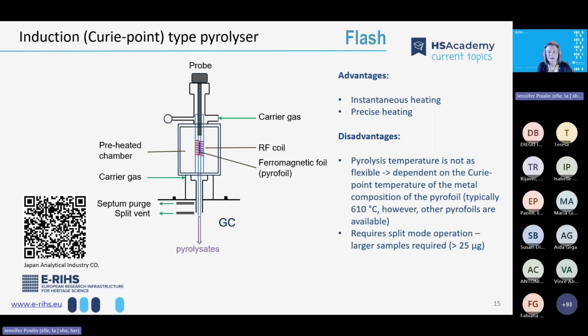So this is the induction type pyrolyzer called a Curie point. It heats a foil using a high frequency magnetic field, and depending on the Curie point of that foil, that's the temperature that you get. In our field, Curie point analysis is generally performed at 610 degrees Celsius. The advantages are you get instantaneous heating and it's very precise. Those foils are calibrated. The disadvantage is that it's not flexible. Depending on the Curie point temperature of the metal of the pyrofoil, that's the temperature that you achieve. However, there are different pyrofoils that are available, so you can get a few other different temperatures. It does require split mode operation, so I think you're going to be looking at samples that are a minimum of 25 micrograms.